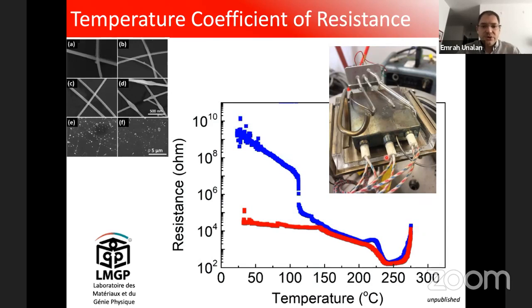And after the deposition, there has to be some treatments. Why? Because even if we remove the polymer, we might have some polymers around the nanowires. Plus, you need to improve the nanowire junctions. So here, as you see, with our French collaborators, this is in situ resistance measurement. As you heat up the thin films, no matter what the starting resistance is, if you reach the temperature of around 250 degrees C on a heated stage, your resistance decreases orders and orders of magnitude.